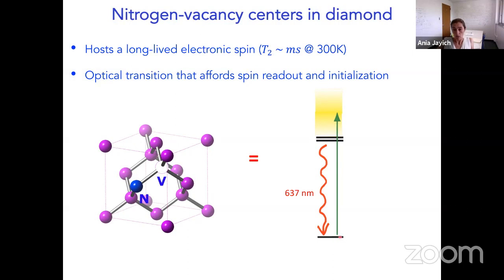Importantly, in addition to that coherence time, there's an optical polarization and optical readout pathway, which allows the value of the spin state to be read out simply via the intensity of the fluorescent photons. Okay, so that kind of summarizes my plug for why we use NV centers in diamond as our model quantum system, again, replicating as best we can an atomic system, but in a solid state, easy to use system.